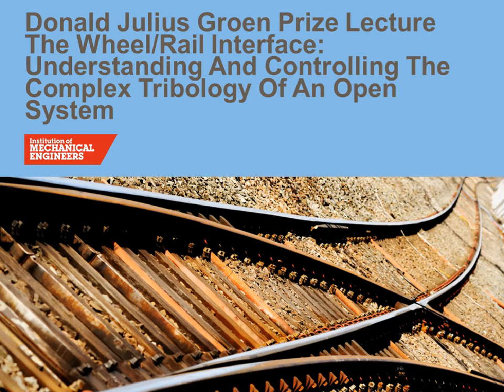in the meantime, just considering the wayside application, you do have to be a little bit careful in terms of reducing how much is applied, because if you run for a while with no grease present and you start to initiate some damage and cracking on the rail surface, if you then reapply grease, you can quite quickly get some accelerated damage as the grease essentially is trapped in the cracks, and you get sort of crack pressurization, and sometimes you can get quite big chunks of material breaking away. We've looked at that in a lab environment, and yeah, the damage can be quite severe if you have a situation where you've got lubricant there and then lubricant not there, and you keep cycling between them. So you have to take care in changing how much you're applying.